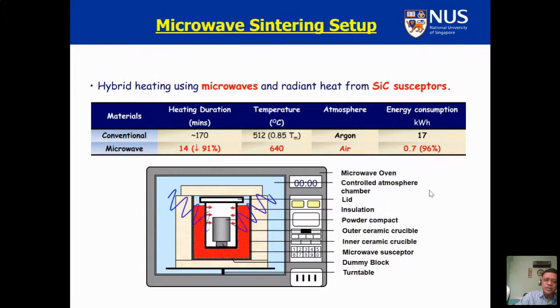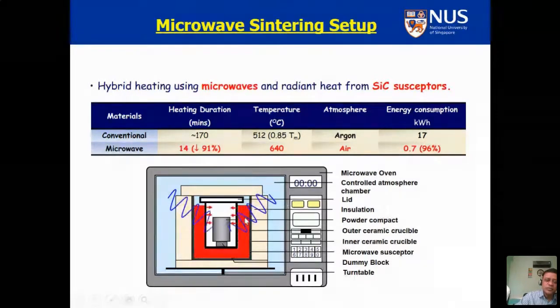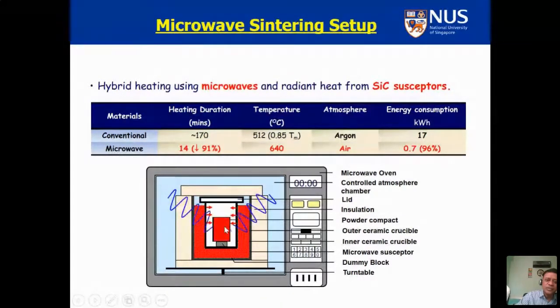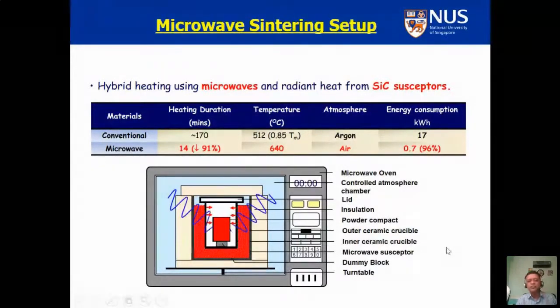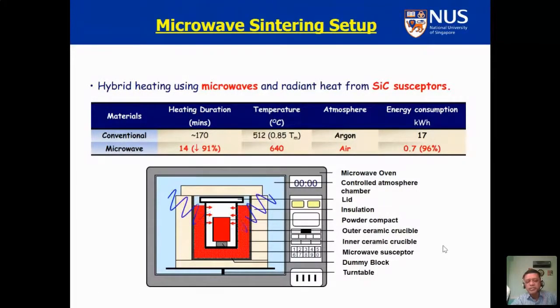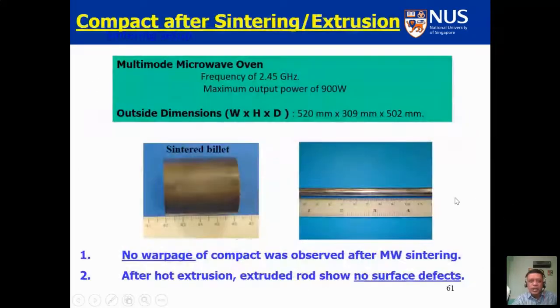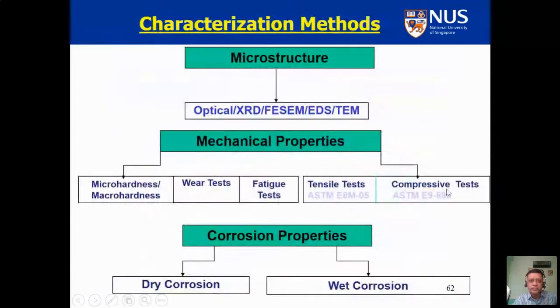This animation shows how the microwave comes and heats the billet from inside to outside as well as outside to inside. So it's a two-way heat front which leads to a very homogeneous temperature distribution. You can get the billet which can be extruded, no defects, nothing, if you do it properly. Now, once you make the material, it is very important to analyze it to ensure that it has the right property which is needed for the end application.